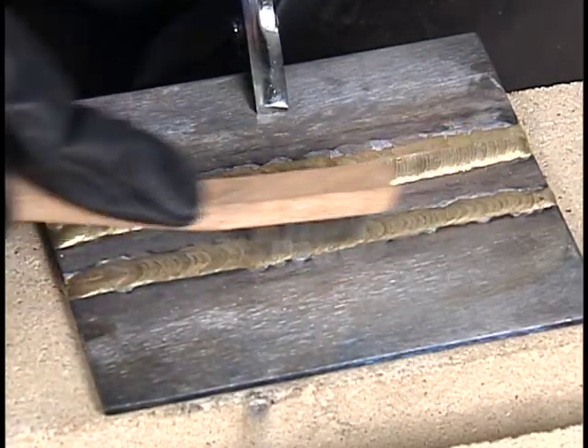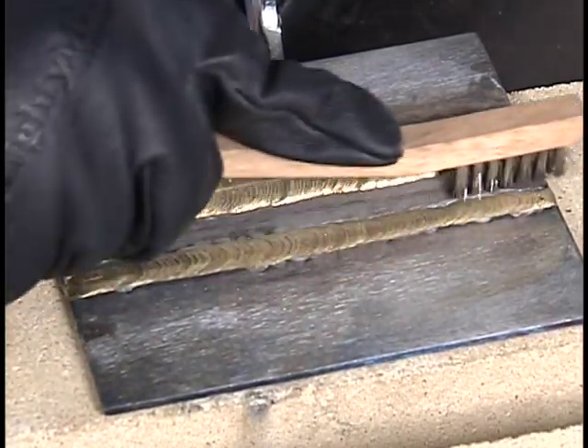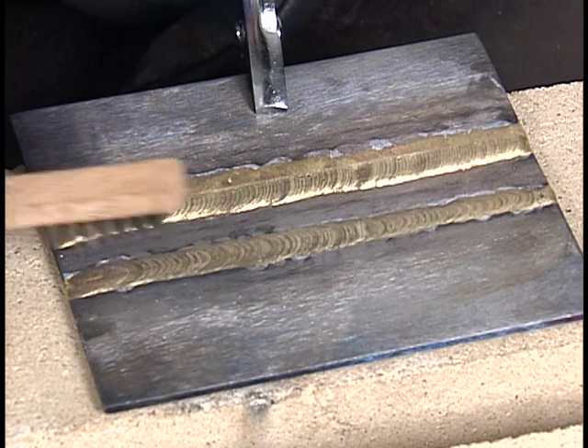However, if you are using pre-fluxed filler rods, continue welding and direct the flame so that the joint is filled completely with the filler metal to produce a braze weld that is approximately 3/8 to 1/2 inch in width. When the braze weld is complete, clean the excess flux from the workpiece with a wire brush.